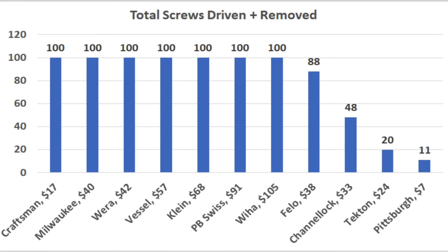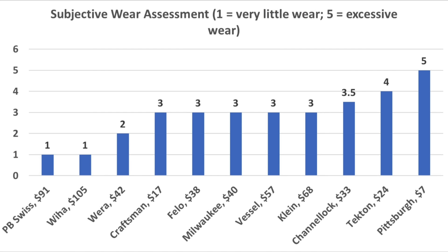7 of the 11 brands survived and completed the accelerated wear test, but the amount of wear varied quite a bit. Assessing wear is highly subjective, but the Wiha and the PB Swiss came in on top with a wear rating of 1. The Wera brand performed nearly as well with a rating of 2.